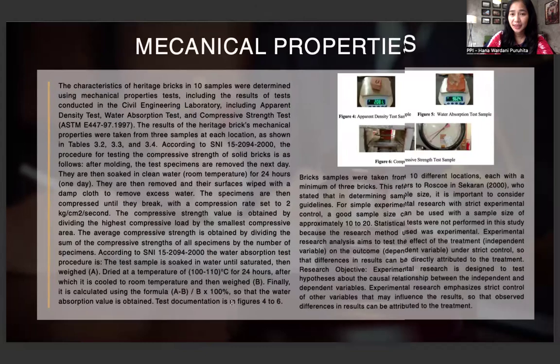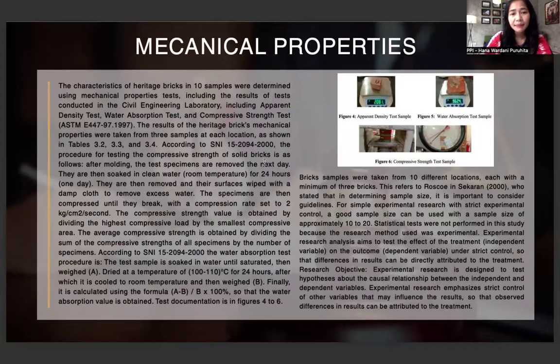And then mechanical properties, we can see many tests we have. The characteristics of heritage bricks in 10 samples were determined using mechanical properties tests, including the tests conducted in the civil engineering laboratory: apparent density test, water absorption test, and compressive strength test, namely ASTM. The results of the heritage bricks' mechanical properties were taken from 3 samples at each location, as shown in tables 3.2, 3.3, and 3.4.